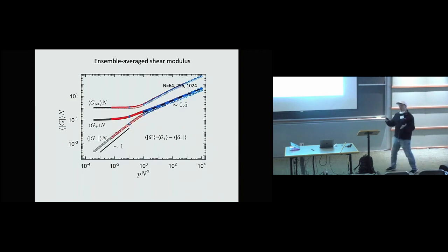So how can a modulus be negative? Some people in the literature say, I don't want to deal with those, don't study those. Literally, that's what they say. But you can have a negative shear modulus. What you do is you just hold the boundaries. If you have an experiment where you fix the strain, then you can stabilize a negative shear modulus, because the system is saying, I want to move, but you're fixing the boundaries, so it's not going to move. The way to get negative shear moduli is to have an experiment where you're fixing the boundaries and not letting them move.